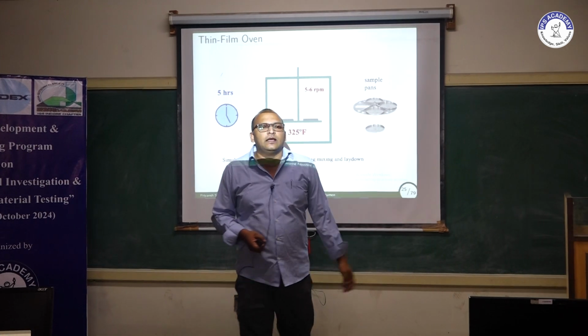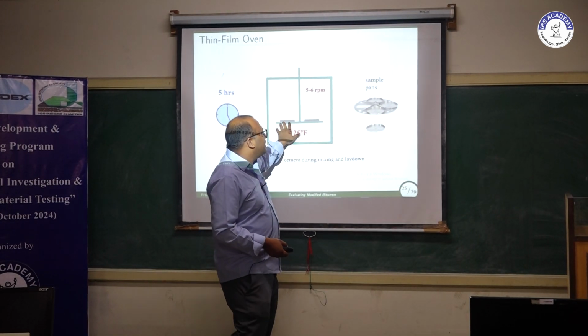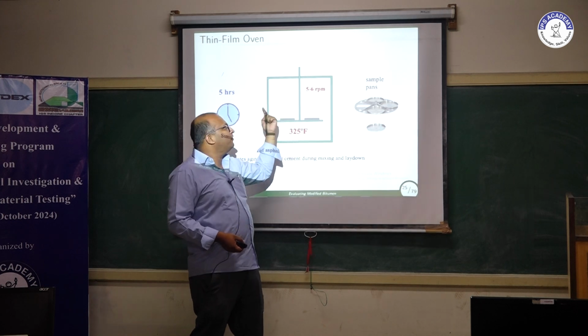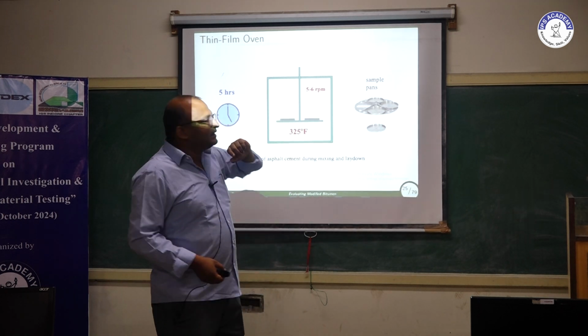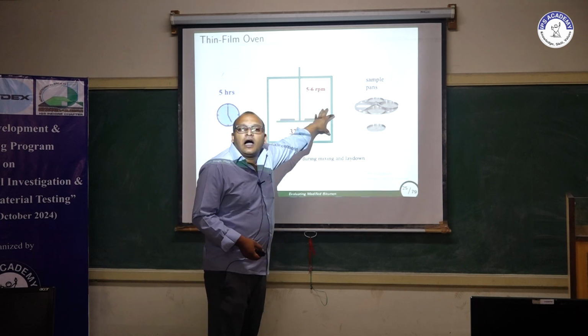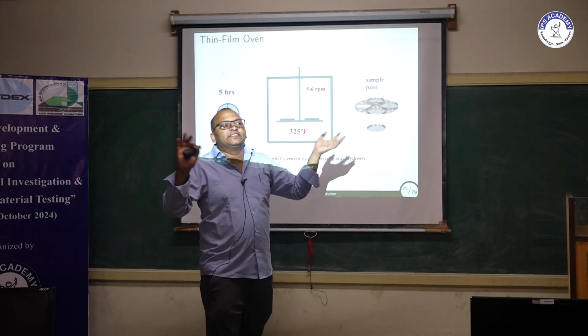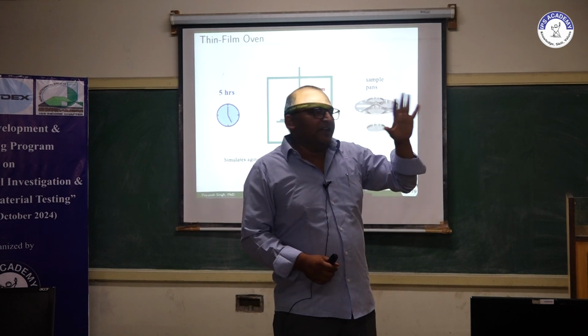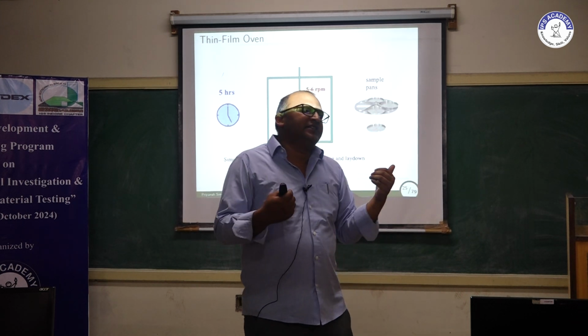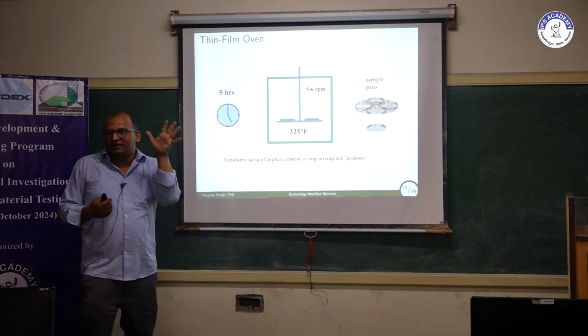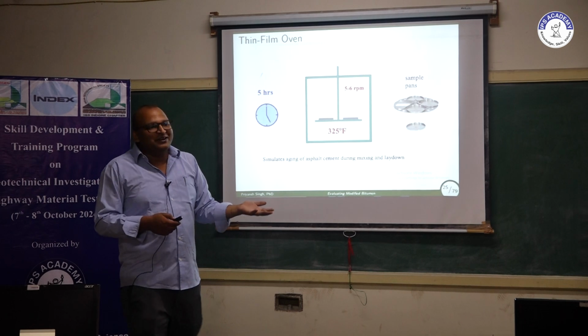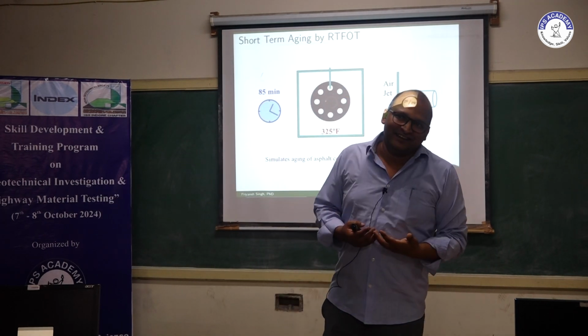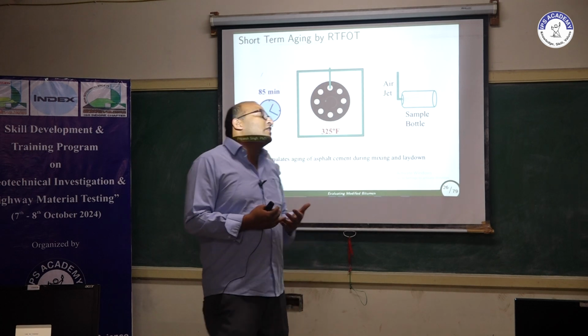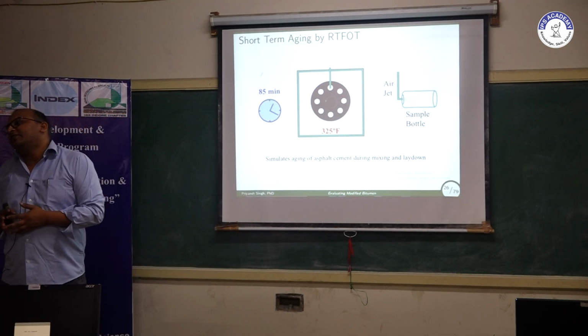In this plate we will put around 30 grams of binder, and then we will put it in this larger plate, and this plate will rotate with a speed of 5 to 6 rpm. At the same time we will expose a high temperature to it. That temperature will be around 163 degrees Celsius, and we will keep this binder for 5 hours, and that is going to simulate our short term aging. Now in this test we require 5 hours of time, and nowadays nobody has time. So in order to reduce the time, there is a modified version of this thin film oven test, called the rolling thin film oven test.